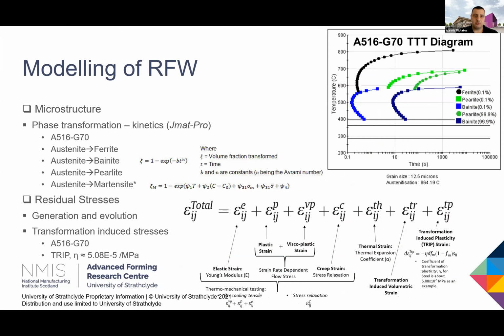Again, with microstructure, phase transformations, the kinetics can be predicted from JMatPro. Pretty standard work created the TTT curves for transformation from austenite to bainite. For martensite, we have a different type of equations, but at the end of the day, these data are available, and we can see the reason why we are getting those bainitic microstructures simply because of the cooling rate and the starting temperature for bainitic transformation. Everything goes into that equation that I have displayed earlier. We need to take into account thermal strain, volumetric transformation, and transformation-induced plasticity. If we do that, we are getting closer.